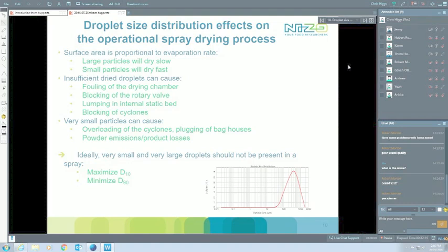On the other hand, if we get very small particles, yes, they will dry nice and quickly, but we're going to completely overload the cyclones. You might get plugging in the baghouses even, you could get a lot of powder emissions, and also when we look later at functionality, we don't want that either. The small particles typically dissolve very poorly, so it's really about controlling that particle size distribution. It's about seeing where we want to be. Typically, the size of a decent agglomerated powder is 200 micrometers, something like that, very nice, but it's also about looking at the edges there.